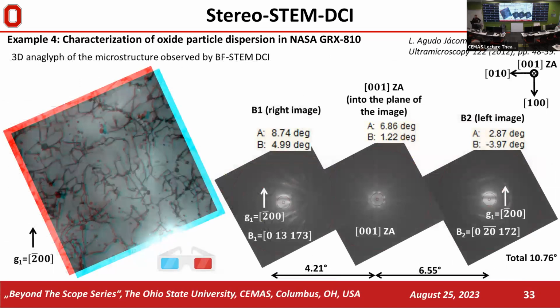So let's just talk about how practically you can get the information and what kind of information you can get if you use this approach. As I was talking before, we usually start with zone axis imaging. We do bright field STEM DCI to image the structure. If you start from zone axis, this gives you a space to later tilt the sample to use two-beam conditions, and that's what we are looking for. So we first collect the data with the [001] zone axis, and then we tilt using the 200 g-vector, we tilt right, we tilt left, and based on theory, to get a nice 3D anaglyph for the human eye, the distance between these two images with two different tilts has to be around 10 degrees to have ideal contrast and visibility.